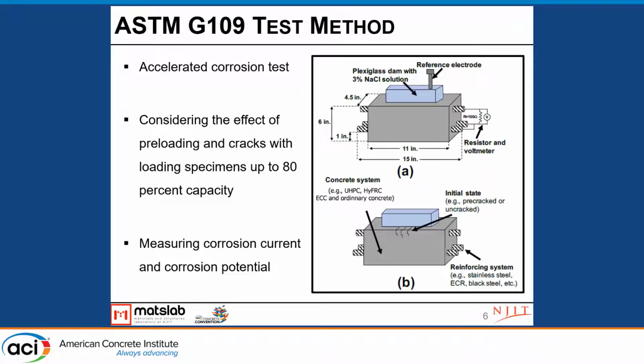Because we want to consider the cracking effect of these materials on the corrosion performance, we are going to test these materials in both uncracked and cracked stages. So we use flexural loading to create cracks in the beams, loading these specimens up to 80% of the capacity, and monitor the corrosion performance and behavior of these materials using corrosion current measurements and corrosion potential versus a reference electrode.